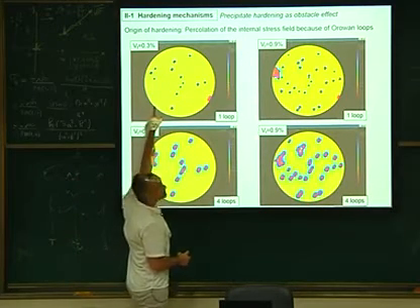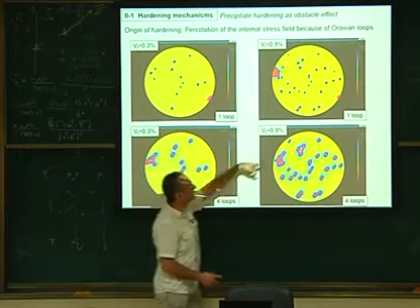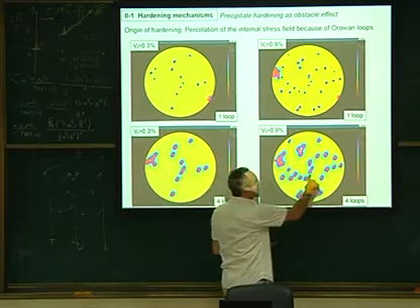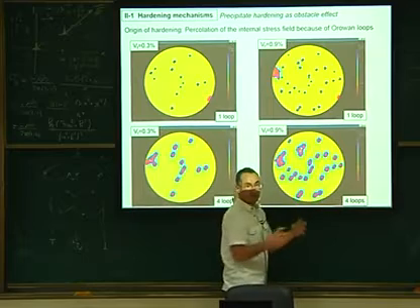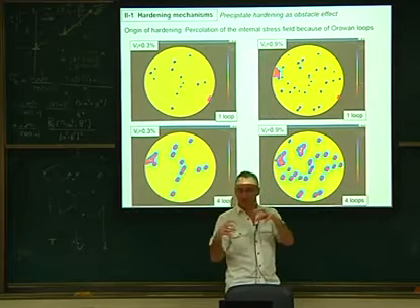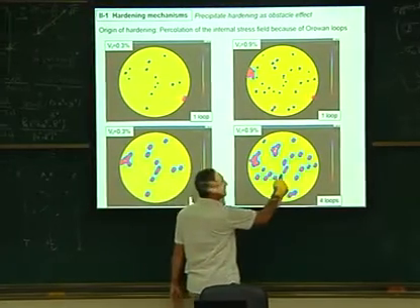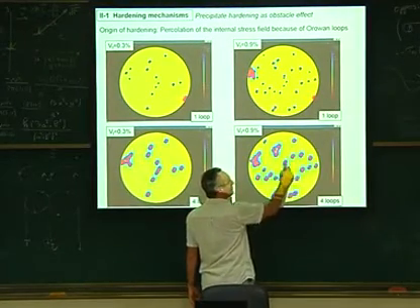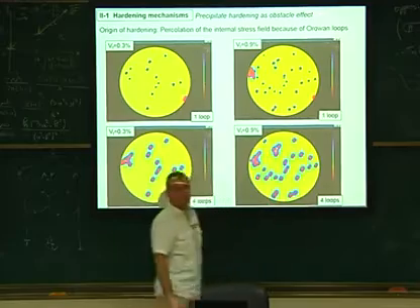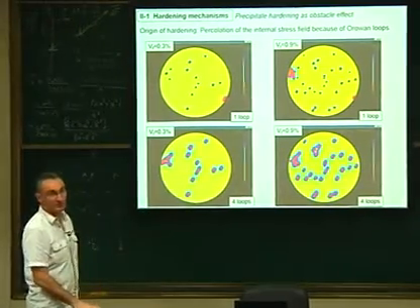Initially, for a small volume fraction, you have a few particles, and you have some Orowan loops. When you have a large amount of particles, then because of the local stresses, they merge together. It's like if the two particles were just one big one, because you have many loops touching each other with the stress field. There is a kind of coalescence of the stresses between the particles when you have too many particles. So this is a mechanism that is important for precipitate hardening.